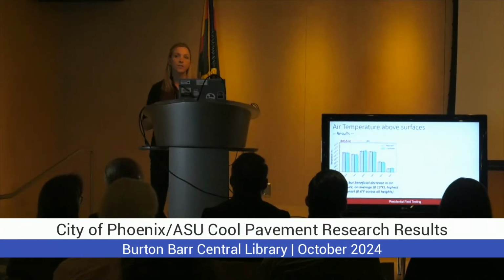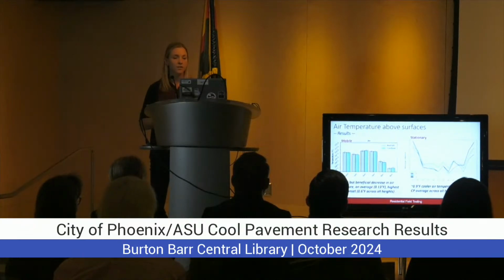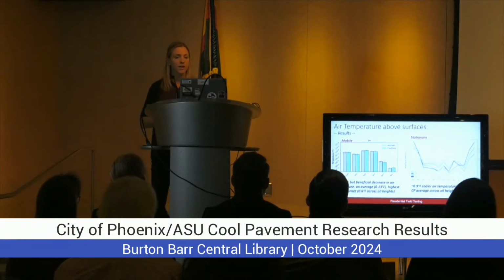So with the results, we overall see a minor but beneficial decrease in air temperature at all of those heights, about 0.13 degrees Fahrenheit on average. And it was the highest after sunset, about 0.6 degrees Fahrenheit, which is similar to the results we found in 2020. If we look at the stationary results, we saw about 0.9 degrees Fahrenheit cooler in the cool sealed neighborhood across all heights.